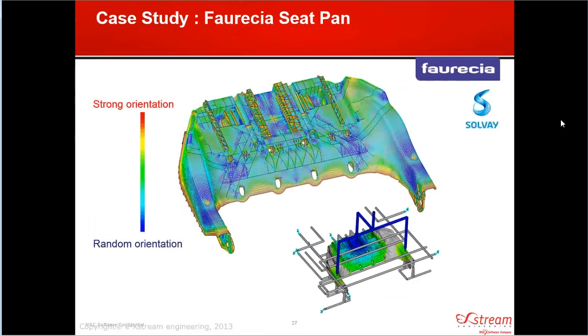On the next page, we see the results from the injection molding simulation. You see that the fiber orientations vary, where the areas that are blue are the more randomly oriented fibers, and the areas that are red are the more transversely or highly aligned fibers. You have a wide variety of those fiber orientation scenarios happening across the part. This is a good indication that a tool like Digimat is going to be very powerful with this type of analysis, because just as those fiber orientations vary through the part, so will the material properties.